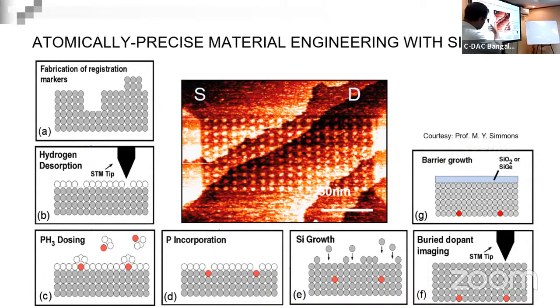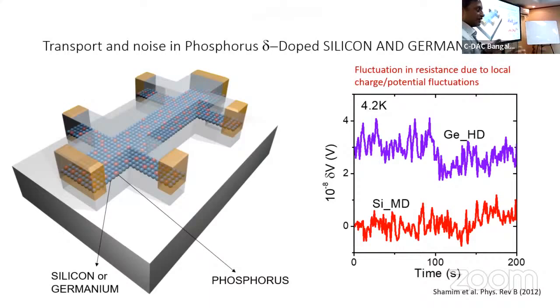What we started doing on these systems is measuring noise. Now, the interesting component here is this is not aluminum oxide, but this is doped silicon, doped phosphorus, which is entirely surrounded by a crystalline silicon environment. So there is no oxide or other bad charges that float around. We found that fluctuations, very simply, you pass a current between two ends, these golden regions are the gold electrodes. I pass current here and measure the voltage. And the phosphorus atoms are down there embedded somewhere. The blue is silicon, in the big three-dimensional matrix. Phosphorus is red, which is essentially confined in a plane, wherever you want.